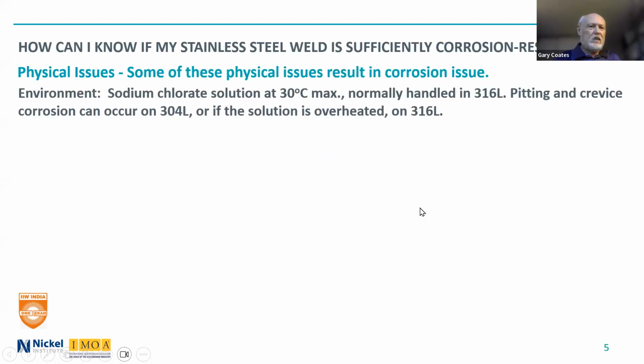So some of these physical issues, for example, I went to a plant, a pulp and paper mill. They had sodium chlorate solution in a pipe at 30 degrees C max. That's normally handled in 316L. We know that pitting and crevice corrosion can occur on 304L, or if the solution is overheated on 316L, but normally 316L is perfect.